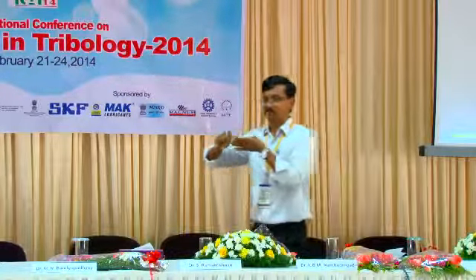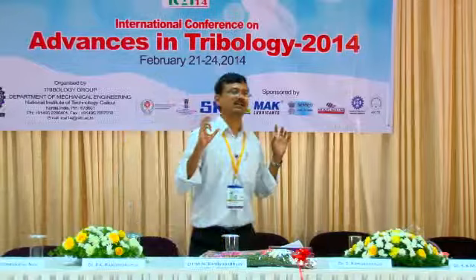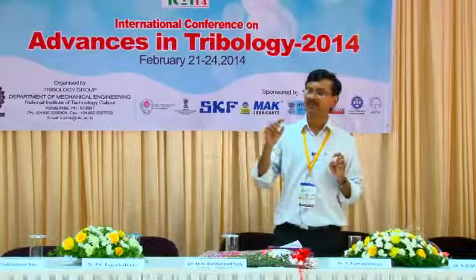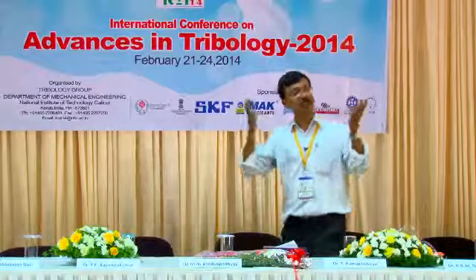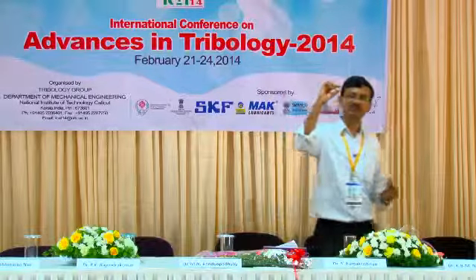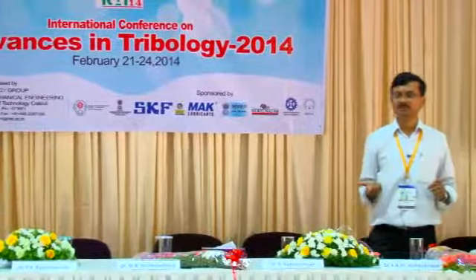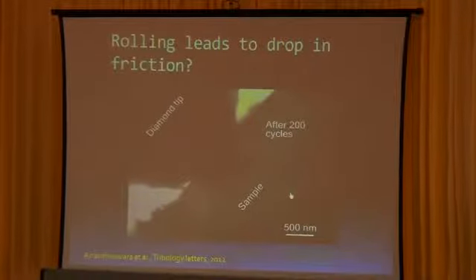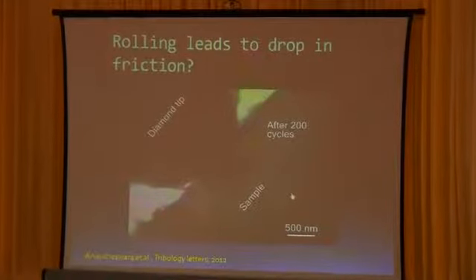We tried nanoparticles deposited on the surface. We wanted them to roll. Okay, we tried everything, but the problem is nanoparticles are hard. Even gold nanoparticles are hard because they are not deformable, as there are no defects in them. You cannot have a dislocation inside a 50 nanometer gold nanoparticle. They are not spherical, first of all; they are angular because of the crystal structure. When you try to roll, they just get impregnated into the material. They slide rather than roll. Rolling is very, very difficult.